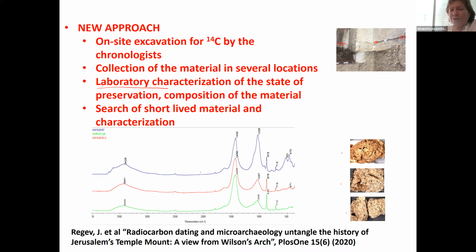You see that, for example, here you have much higher clay than in this case. And here the clay is not burnt because we still have the peak of the structural water, while in this case it seems that the clay was indeed burnt.